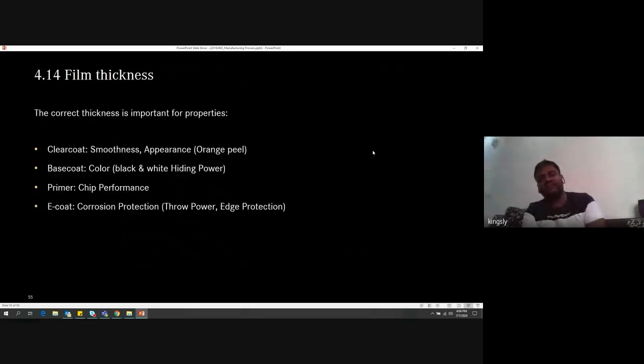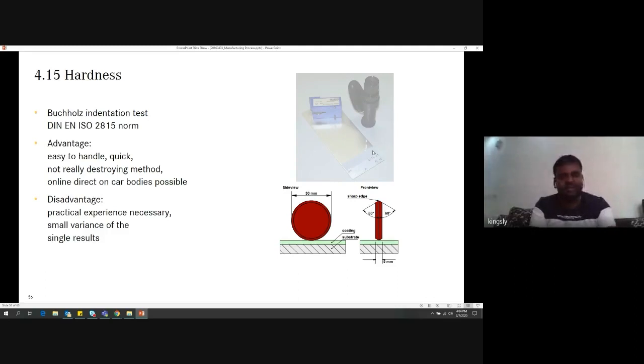Because this thickness is important. If the thickness is low, then there is no guarantee that it won't get corroded. If the thickness is okay, we can give the guarantee that this paint will withstand for 10 years. Then the hardness is also important, because if the hardness is not good, then the paint gets cracks. So after all these tests, we also do the hardness test.